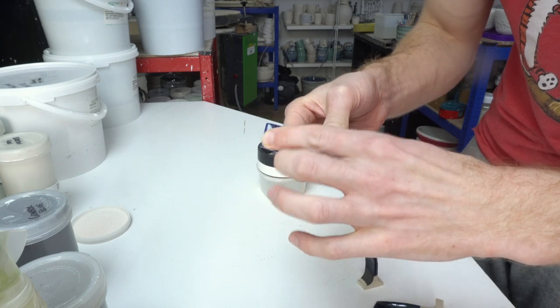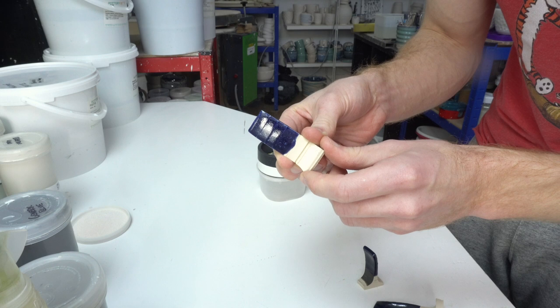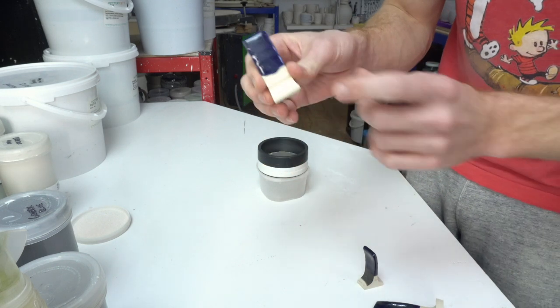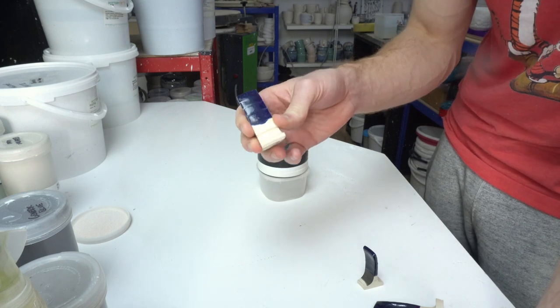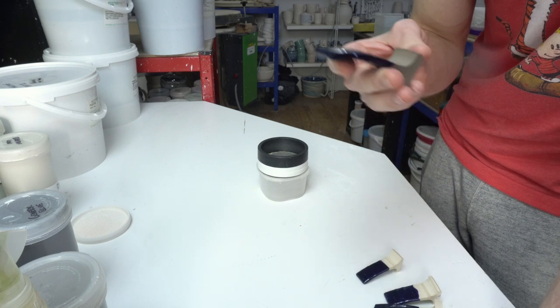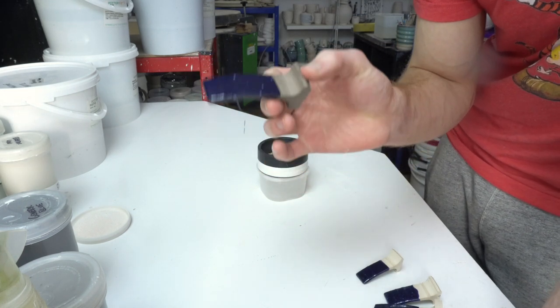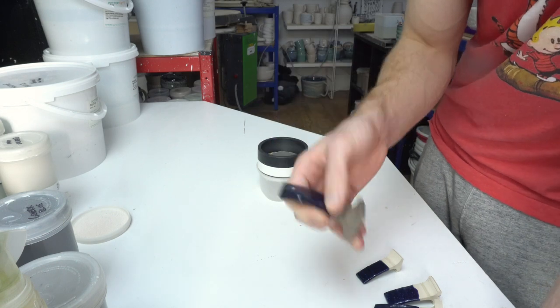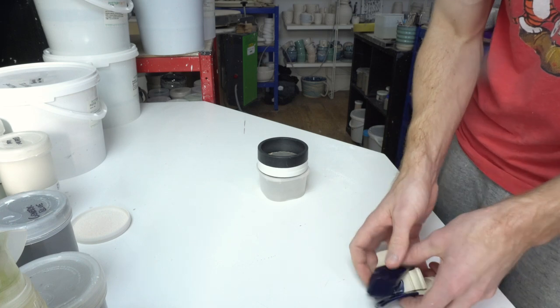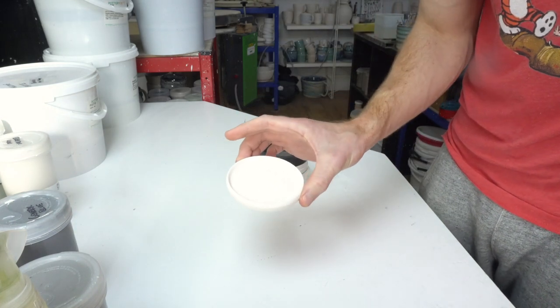Hopefully you can see you're getting some nice speckles in there. Also, the surface quality isn't quite as glossy smooth as I'd like, which I'm hoping having less cobalt and using cobalt carbonate rather than cobalt oxide will help with. So I've got revised ones of those, and then these are with bigger sprinkles, which there are far fewer of because they're heavier and sink to the bottom. They don't get taken up in the same way. So I'm going to stick with the fine sprinkles, which I now have more of.